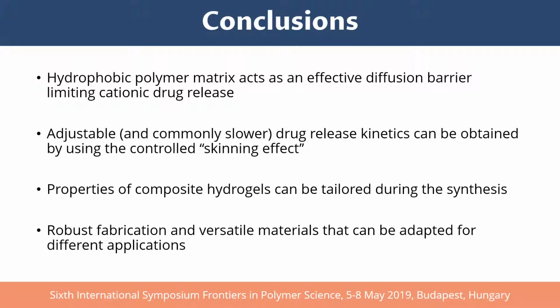We can draw several conclusions from our research. Hydrophobic polymer matrix in the composite reservoir acts as an effective diffusion barrier, limiting cationic drug release. Adjustable and commonly slower drug release kinetics can be obtained by using the controlled skinning effect.